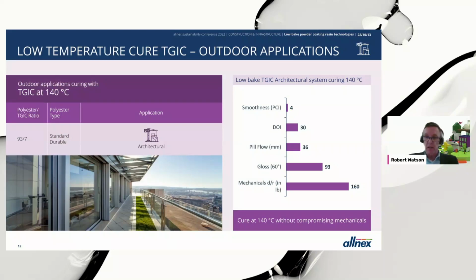We can take triglycidyl isocyanurate and see the kind of examples we have here. So again, it's a standard durable polyester for architectural curing, outdoor applications. This particular one is a 93:7 ratio. And over on the right-hand side, we can see that what we've got from the gloss level, it's a high gloss system, we can see acceptable smoothness, acceptable distinction of image, but at the bottom we can see the mechanical performance. So this is an impact test where we hit the panel either direct or indirect. And when we get to a level of 160 inch-pounds, we're starting to see the substrate fail before the coating fails. So again, when we step back and we say, well, are our coatings meeting the performance criteria? We can say yes. So 140 degrees, it's possible to cure with TGIC without any compromise in the mechanicals.